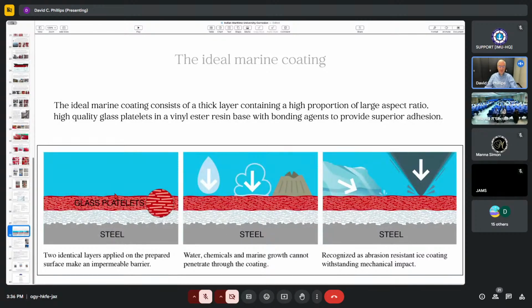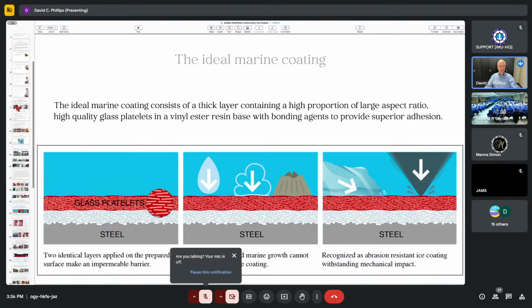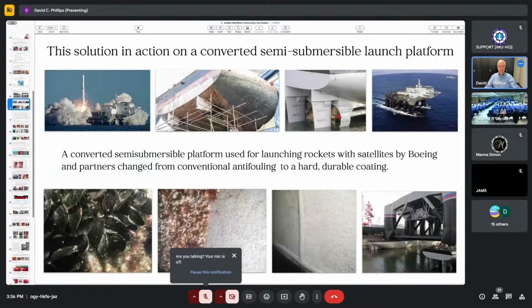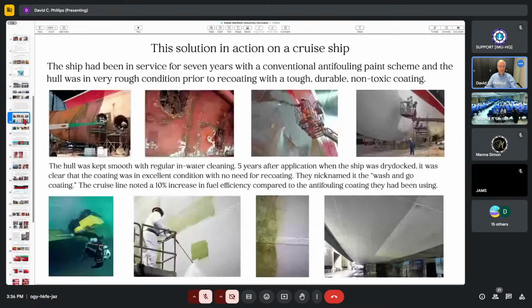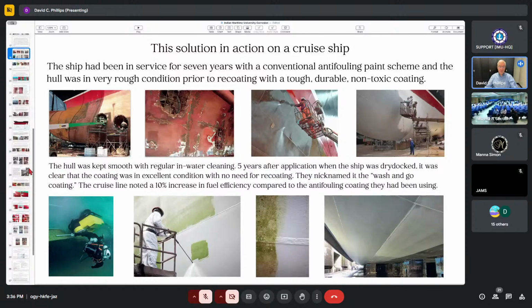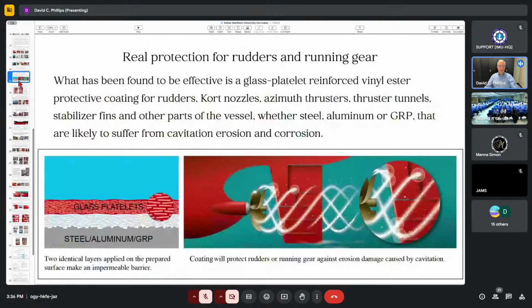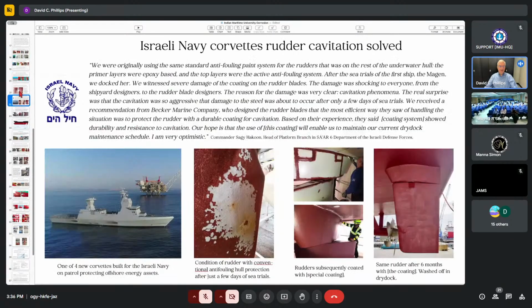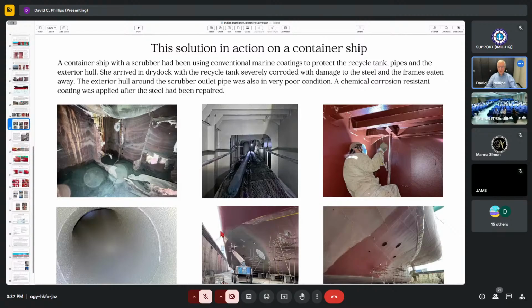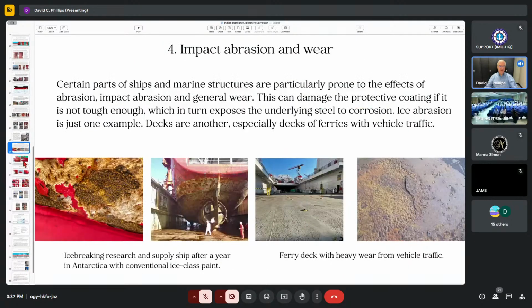Okay, so now I'm going to tell you about this particular coating that I've actually been referring to in all these examples so far. It's the same basic coating that was used here, and here, and almost the same coating that was used on the rudders and running gear, although there's a slightly different proportion of glass to vinyl ester in that one. Makes it a bit tougher, which is why it's special for cavitation. But all of these, the same chemical corrosion, same coating, and abrasion resistance coating, ice going coating, the same.